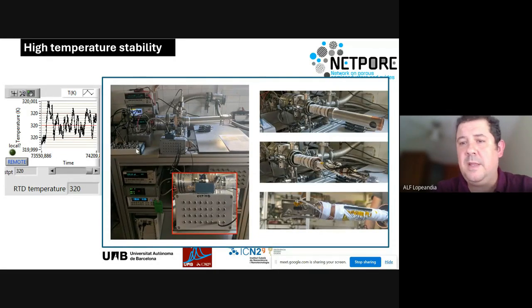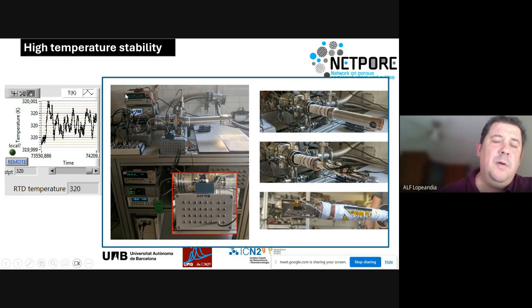And in that case, we use a helium cryostat. In that case, we have changed the control setup. We skip the commercial one, and we developed a PC-based temperature control, PID control, with high resolution sources in order to get stabilities of around 1 millikelvin. With 1 Kelvin, we could not measure anything.